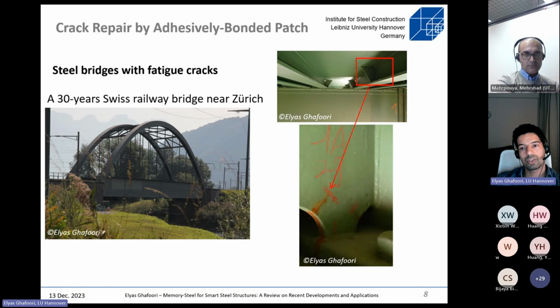I'm showing you also other applications. Here we have a relatively young bridge. In civil engineering we normally design bridges for up to 100 years, but this bridge near Zurich has more than 30 cracks in different parts, small cracks in complex details, and there is no way actually to stop those cracks. This is a railway bridge, and these cracks grow until they reach a critical size, and then there will be failure of the part, not the whole bridge, of course. But if there are many cracks, then it becomes critical.